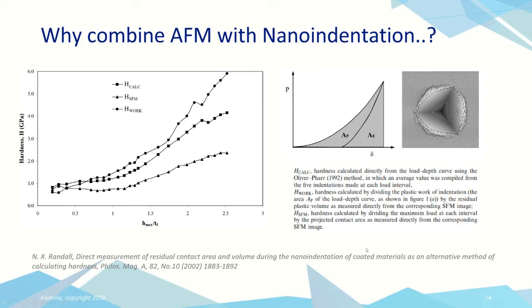The third method is what we call HSFM, and this is the hardness calculated by dividing the maximum load of each indent by the projected contact area, but not measured from the curve, measured directly again from the AFM image. So we're basically measuring the area defined by this dotted line. And so this gives us a hardness calculation which takes into account the pileup around the material.